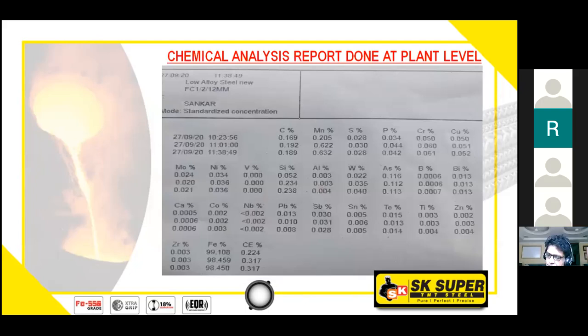See, there were 3 tests done. First was at 10:23, second was at 11:01, third one was at 11:38. The 10:23 test was for the raw material, the 11:01 was for the billet, and the 11:38 one was for the TMT. So if you see the time frame, within 1 hour 15 minutes, right from melting of the raw material, you are getting the finished products. And especially have a look at the percentage of carbon, sulfur, and phosphorus. It is changing at every level. At every one of the 3 different levels, it has a different value.